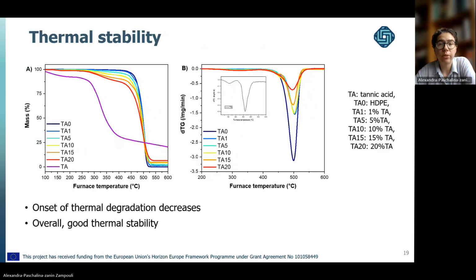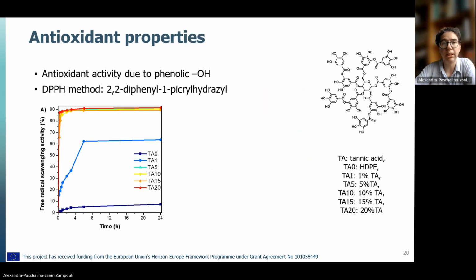Thermal stability was further studied. So we can see that tannic acid, which is this purple curve, is less stable than HDPE. And the onset of thermal degradation decreases proportionally with increasing tannic acid content. The temperature of maximum degradation is not much affected. So overall, we can say that the composite retained a good thermal stability.